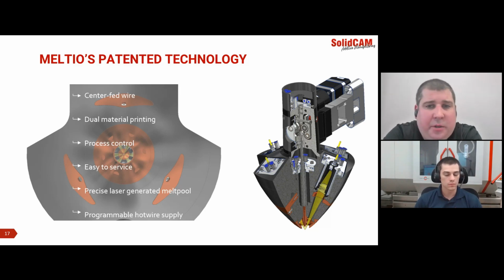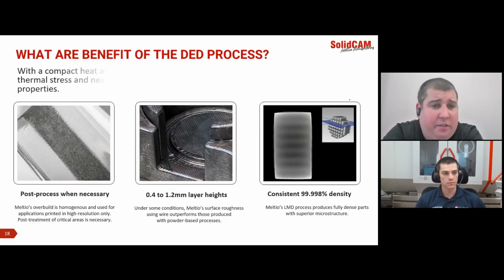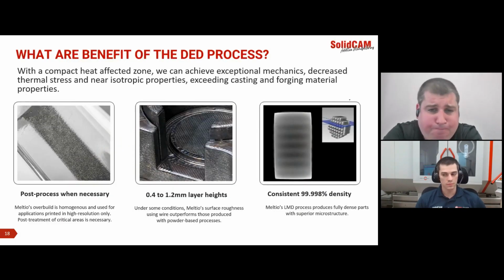And what this allows us to do is feed in any direction. So we can feed in any XYZ combination as well as multi-axis deposition, where some technologies out there with side-fed wire force you to feed in one direction, where you need to have essentially the feedstock behind the melt pool, where because we're center fed, that issue goes away. It makes programming of this technology very straightforward, very similar to any other CNC toolpath in terms of process flow, just using particular additive toolpaths. Very easy to service with a redundancy of 6 lasers as well.